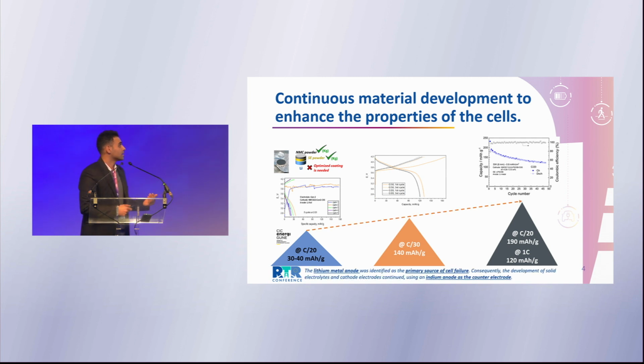But the main challenge that we have identified is that the lithium metal anode was considered as the main challenge because it was very difficult to source lithium metal anode with high quality, and also the coating of this was very challenging. So as an intermediate solution, we proceeded to make cells with indium anode. This allows us to fabricate cathode electrodes, solid electrolyte layer, and fabricate the first cells with the indium anode. And later, when we have the lithium metal anode, we can fabricate the final cells with the lithium metal anode.